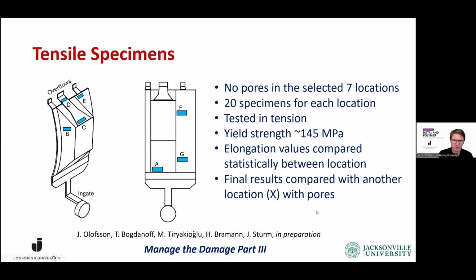But then we wanted to see, is there a difference between the different locations? Are they actually behaving differently, or are the samples that we take from the same distribution or from different distributions? Do properties change with location, as in this case? The final results that come out of this, we also compare to another location where we have visible porosity, because I forgot to mention that in these 7 positions that we're looking at here, it has been confirmed by CT scanning of these samples that there are no pores, to make sure that there is no visible damage in these locations.